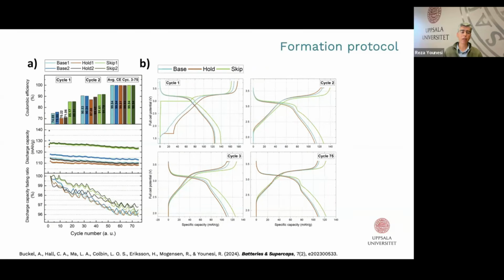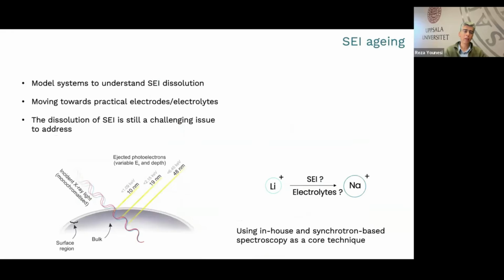Here you see the results. For each chemistry and each protocol, we tested at least 3 different cells to make sure we have full control of the error bar and reproducible results. This is a major issue in battery literature, so I really recommend everyone here, if you're working with batteries and making cells, make sure you make at least 3 cells for each experiment to present the error in the measurements.